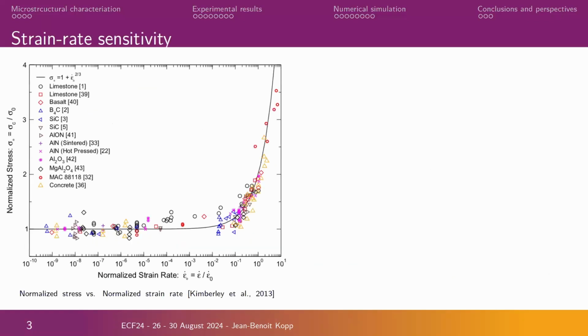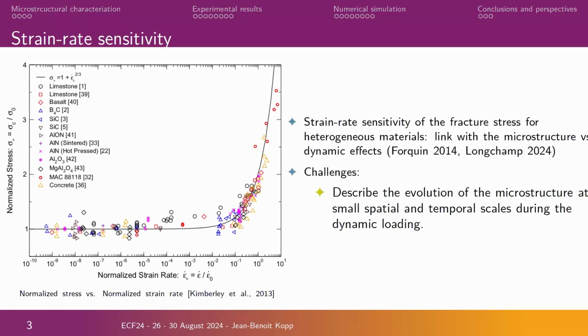Because in the literature, this kind of diagram is well known, which concerns the evolution of the fracture stress or the limit strength as a function of the strain rate. This kind of evolution during a dynamic regime, with a quite strong increase of the fracture properties, is well known in the literature. And the explanation is possible thanks to micromechanical models and numerical prediction. So we explain this increase by the link between heterogeneities, microstructure, and the dynamic effects of damage and dynamic loading. But finally, it's quite complicated, especially for brittle ceramics, to describe experimentally the evolution of the microstructure under the dynamic regime.